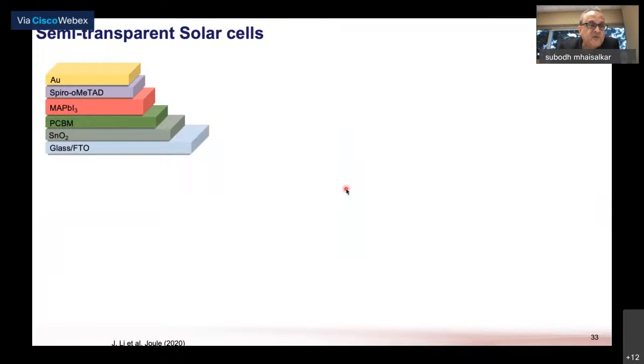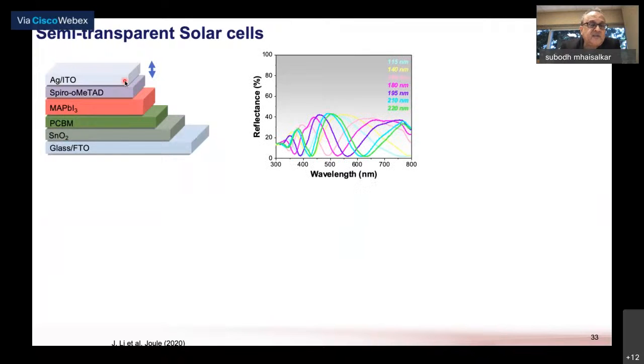But before you go on to the modules, one of the other questions to answer is if these need to be integrated with silicon, you really need to take into account the possibility of semi-transparent solar cells. So far, the cell structure that I've shared with you has gold on it. So we really had to replace the gold. In this case, we replaced the gold with a very thin layer of silver and an ITO deposition on top of it. In one of the studies, we also changed the thickness of the ITO so that by changing the thickness, one could also change the conductivity or the resistance of the ITO.